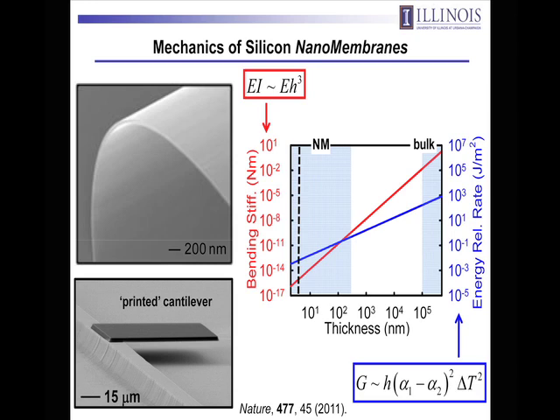The other consequence of mechanics in silicon nanomembranes is a little bit less obvious, but it's equally important when you think about building the systems that I'll talk to you about in the next 10 minutes or so. And that has to do with interface fracture mechanics. So if you take silicon in this very, very thin form, here's an example of a platelet of silicon printed onto a silicon substrate in which we've structured the surface to create this ridge. You actually print this membrane or this cantilevered structure down on top of the wafer, even without any adhesive at all.